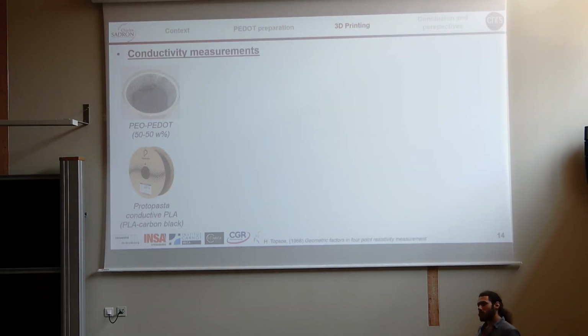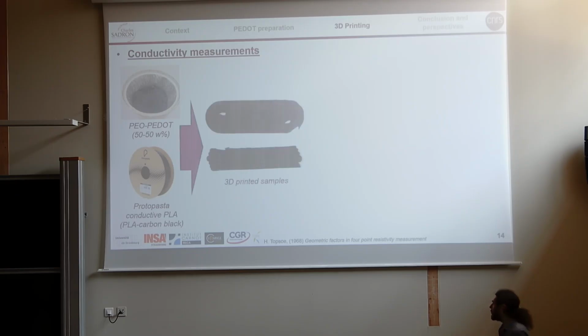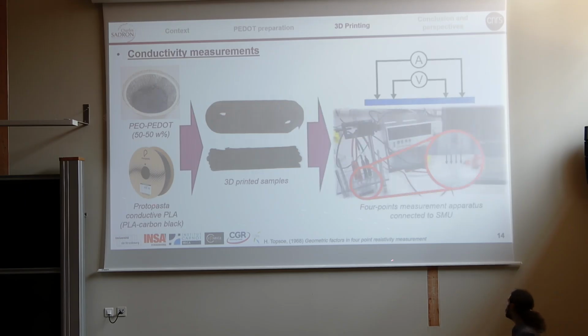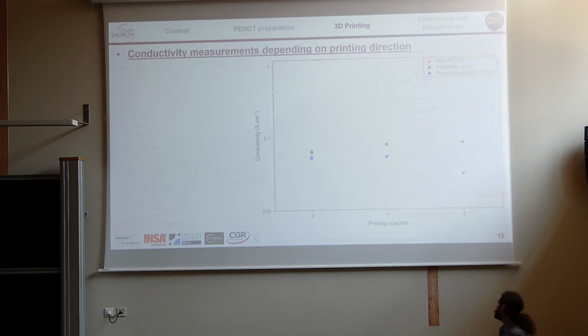So I compared two kinds of materials, our PEDOT composite, but also commercially available Protopasta conductive PLA, which is a PLA filled with about 20% of carbon black. Those are the kind of samples I could obtain using our material. And for the measurements, I used the 4-point apparatus connected to a multimeter. So these are the first results for the Protopasta. So you see that our values are just a bit higher than the values of the supplier.